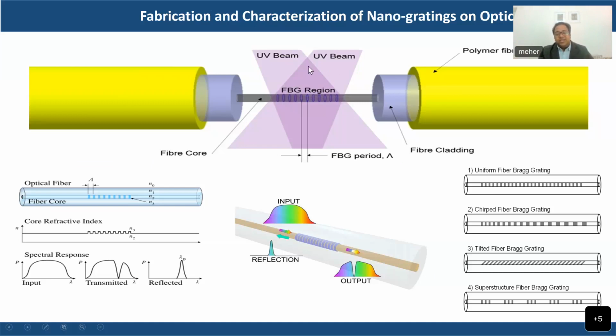So why do we need these patterns? We need them to have peaks, and the peak is very sharp. We can measure the shift in the peak by having some sensing material here. People used different geometries and different dimensions, but the problem is it is not too sensitive. Why not too sensitive? Because the sensing component sits on the surface, and light propagates here in the middle. So the interaction of light with the surrounding material is not that much. So we thought, let us try to increase the interaction area of this device.